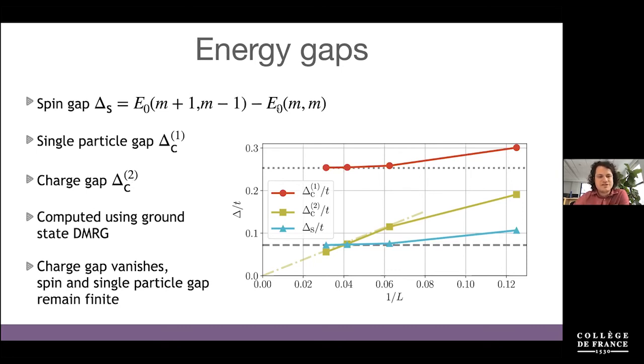Then we can compute these ground state energies using DMRG and look at the value of those gaps. And this is shown here on the right-hand side. Whenever we compute gaps, it's a good idea to study this as a function of system size. So on the x-axis, we have 1 over L, L being the length of the cylinder. And on the y-axis, I'm showing you the gap. Different colors are the different gaps. There's a charge gap shown in olive, there's the spin gap shown in blue, and there's the single particle gap shown in red. Now what we find is, interestingly, that the charge gap actually vanishes. So there are gapless charge excitations. However, the single particle gap remains finite.